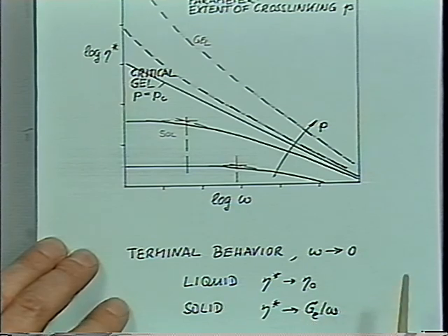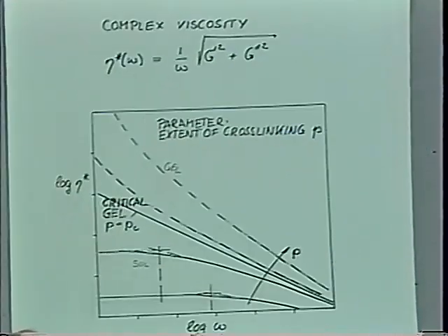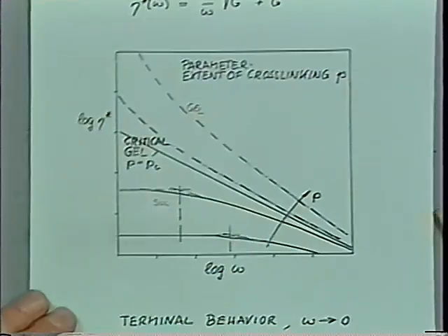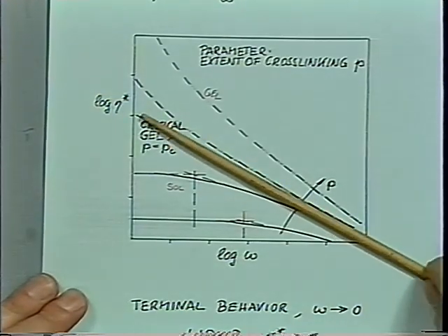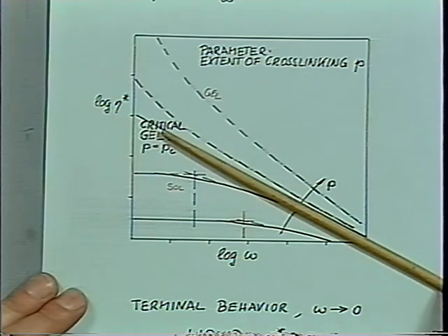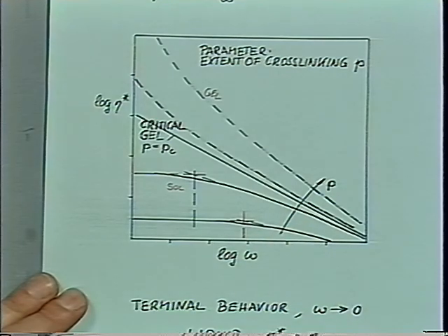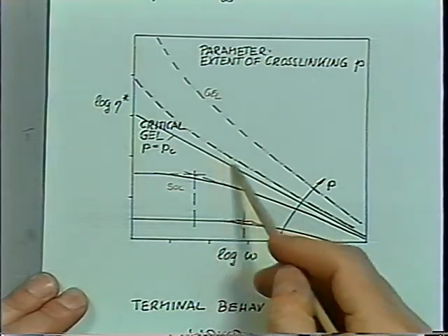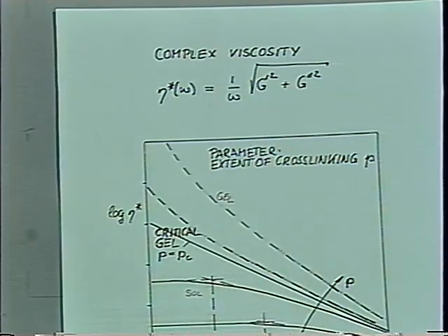There's a question, or no? It has been resolved. Okay, so the typical fingerprint of our gel is the following. The material at the gel point, the critical gel, has a relaxation behavior like this, power law relaxation behavior. The slope is really given by omega to the n minus 1, because we are dividing here by omega, and those guys go with omega to the n.